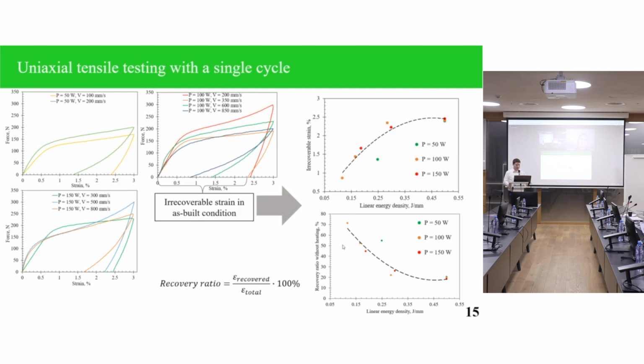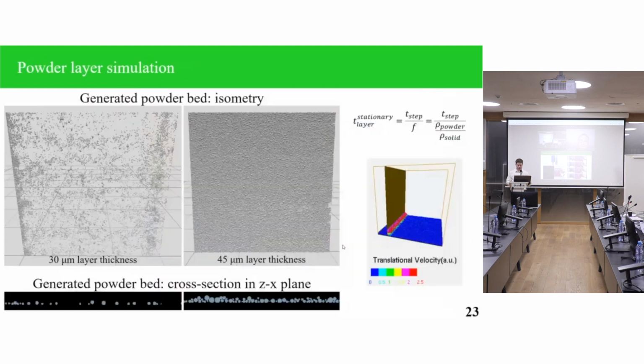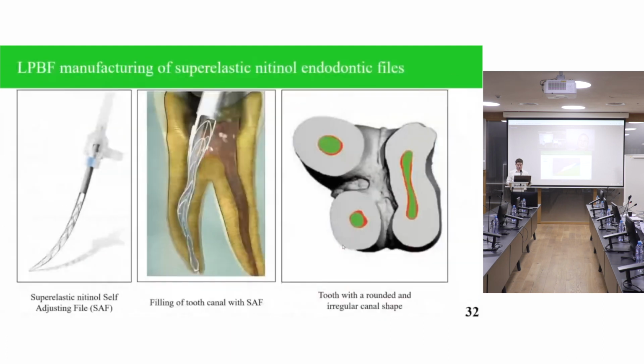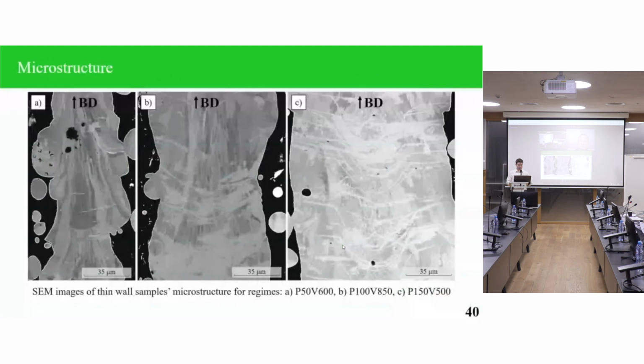But in my case, I have a strong texture for all my samples manufactured by different process conditions. And in this regard, also, I do not use wires, I use plates. So in this case, I didn't observe a strong size effect that can definitely be present for some micron wires. So thank you for your question.